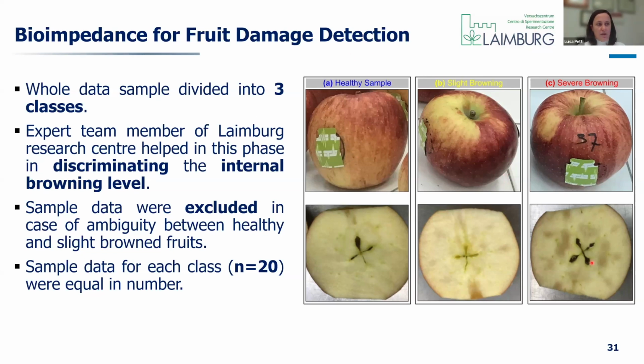and you can see it only if you cut, and also doing destructive tests, in order that an expert team is able to discriminate this and label the data. Sample data that were ambiguous were excluded, and that data set had 20 sample data for each class. Now she's doing more experiments and also learning clearly from the mistakes of the first experiments.